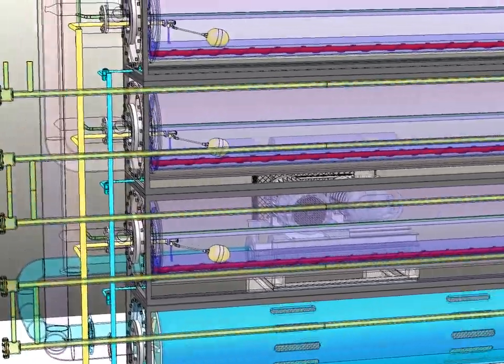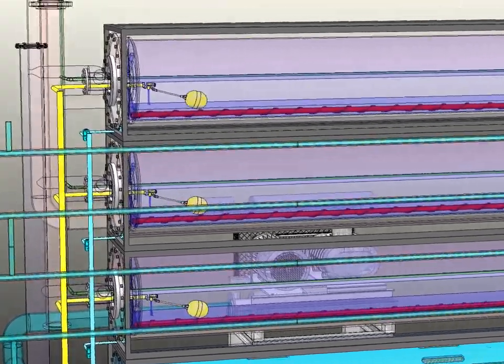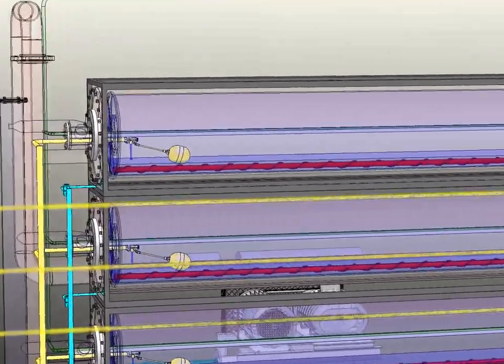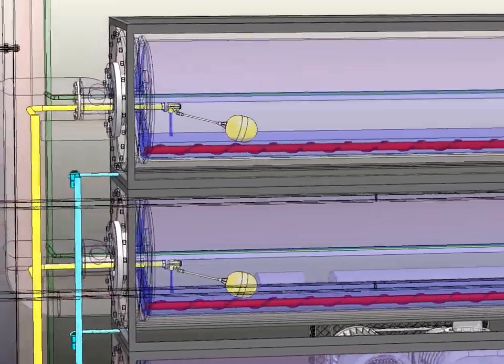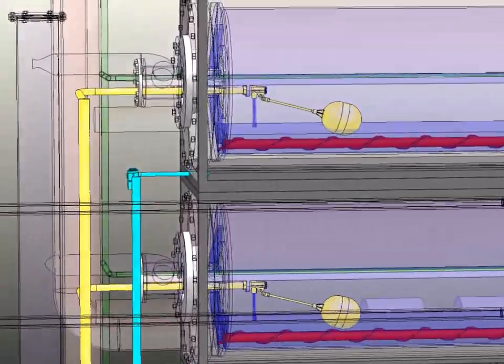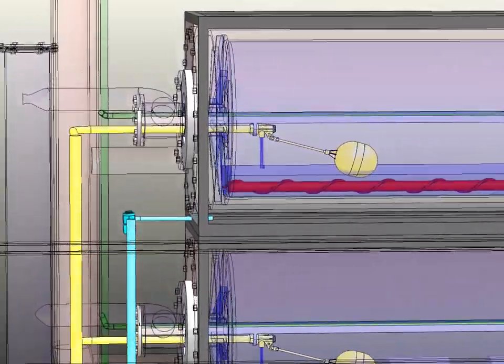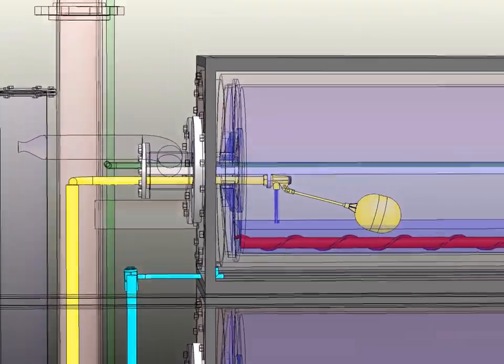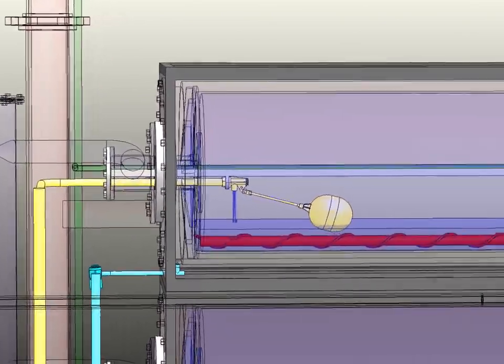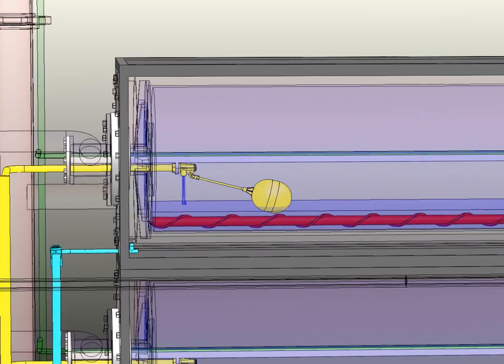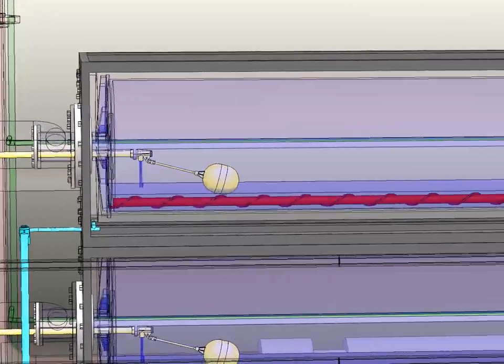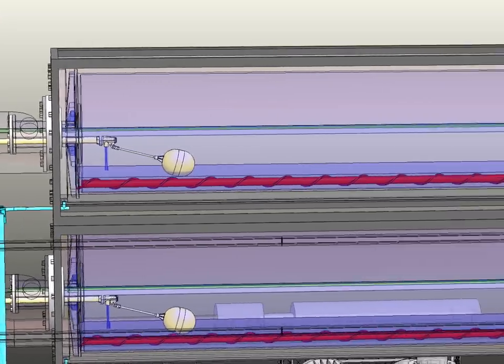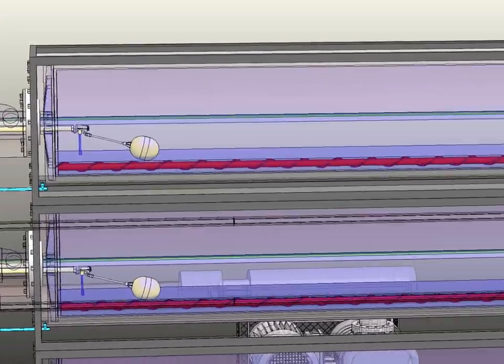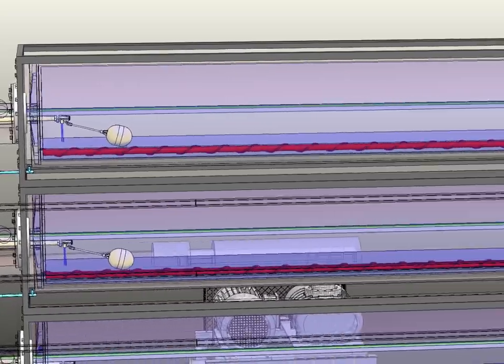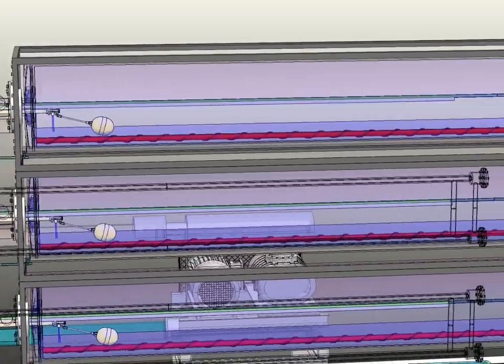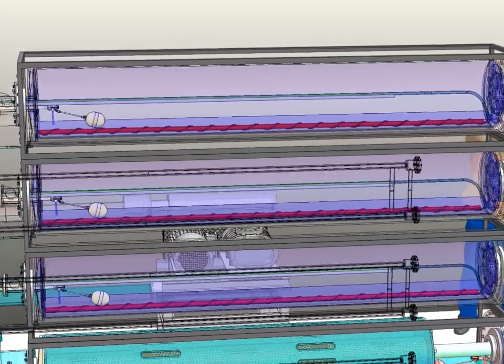The evaporator allows the concentration of solutions to high salinity values, at which precipitates and colloidal particles begin to form. It is colloidal particles in contact with the heating surface that gradually degenerate into solid layers of scale, which impede heat transfer. To prevent the formation of deposits on the surface, the heating surface is constantly cleaned with a rolling rod with a spiral winding. Because it is possible to move this rod in the axial direction, the spiral winding works like an auger, which not only cleans the resulting sediment particles, but also transports them to the concentrate discharge point. This prevents particles from accumulating in the concentrated solution and makes the evaporator resistant to scale formation.